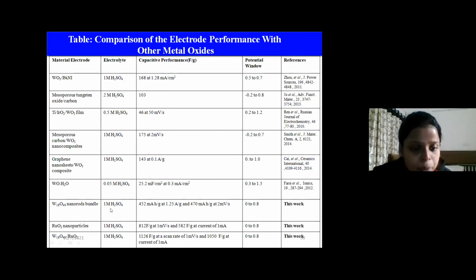Here we can see that the W18O49 is giving 452 milliampere hour per gram of specific capacity. Ruthenium oxide is giving 812 farad per gram of specific capacitance, and the W18O49 hybrid nanomaterial is giving 1126 farad per gram of specific capacitance at a scan rate of 1 millivolt per second in the same potential window. So this shows that because of the synergistic effect of W18O49 and the ruthenium oxide nanoparticles, this hybrid material is giving good properties.